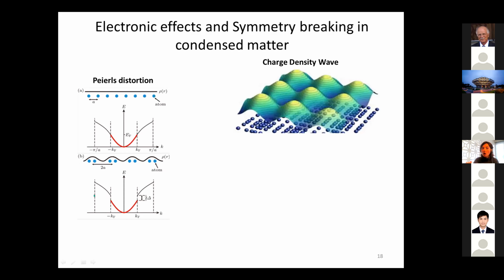First thing. But then there are also other things like charge density waves in higher dimensions, a two-dimensional effect that is basically a static modulation of the lattice. Sometimes it's related to this exact Peierls distortion. The origin of it is that. Sometimes there are other things, like simple energy lowering or shear, that can cause this CDW, charge density waves, which are actually a very important topic in condensed matter, in two-dimensional systems.